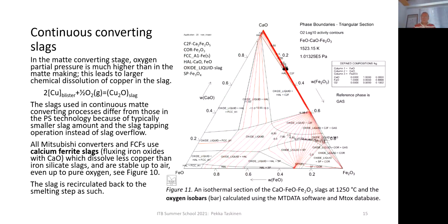So what kind of slag is calcium ferrite slag? What kind of slag is formed if we flux iron oxides with lime? It's important to know how copper is dissolved in this slag, because that is actually the driver, the carrot, why we are using lime fluxing. And lime fluxing comes from the fact that at the same oxygen partial pressure, at the same temperature, it dissolves less copper chemically, and this is one important feature of calcium ferrite slags.